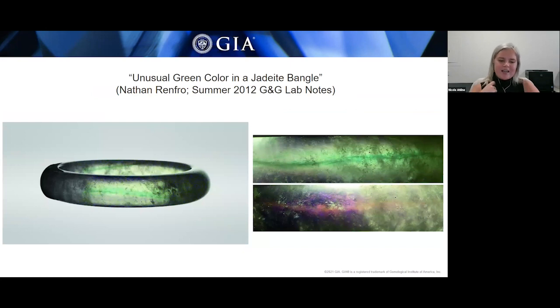So the last piece we'll discuss is the 58.3 gram jadeite bangle, and this was examined at the Carlsbad laboratory, and it showed a very unusual green color through the center of the piece. So it was mottled jadeite with green patches, which is not uncommon and is naturally occurring with chromium, or it can be artificially induced with dye. With the aid of the handheld spectroscope, there were no distinct features for either chromium or dye, which are usually present in that red region of the spectrum.